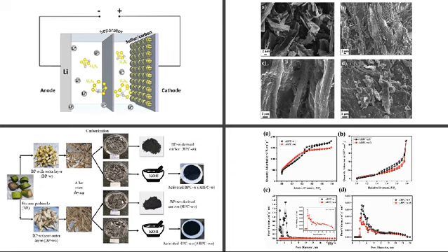So what do polysulfides mean? As I already mentioned, a series of products are forming. These products are called polysulfides. We need to trap these polysulfides in the cathode itself for improving the performance of lithium sulfur battery. Later, we did the adsorption study by preparing polysulfide solution and mixing it with the carbon. We observed that for the activated carbon samples, it adsorbed the polysulfide and the solution color changed to transparent.